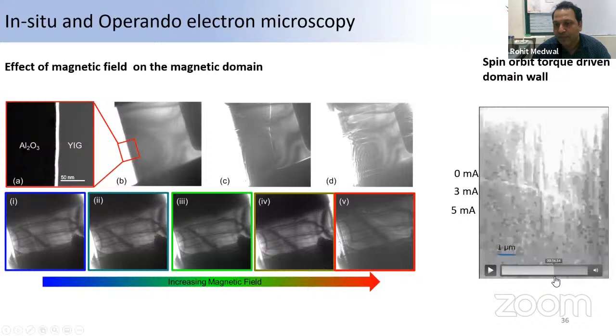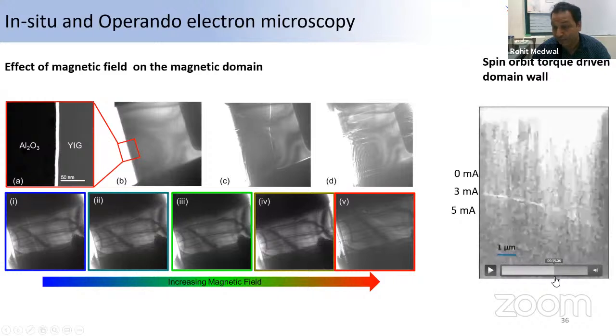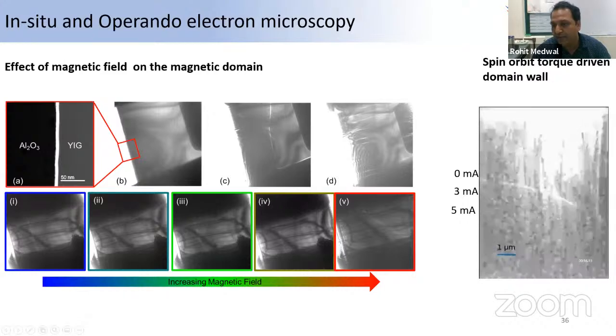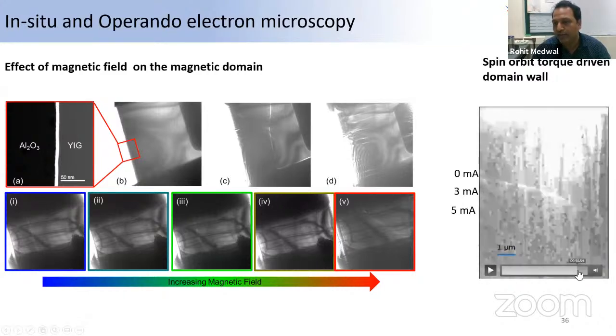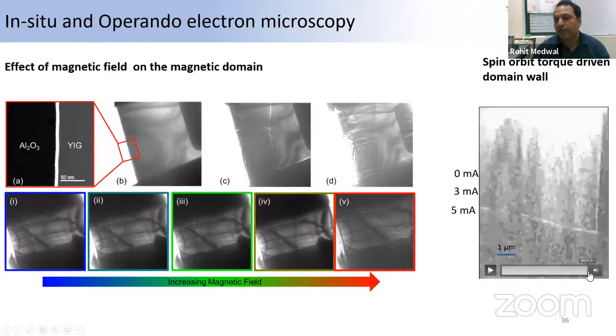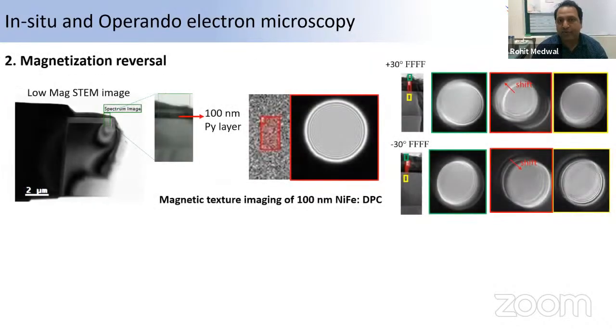You can see here. Maybe I'll stop here. You can see that at 3 milliampere, we can move the domain wall here. And at 5 milliampere, it can really go to the final state, the third state. So we are able to successfully move the domain wall using the pure spin current, and we were able to detect this live in situ in the microscope. With this, we are also able to see the switching of the magnetization from one state to the other using differential phase contrast imaging, where we have this bright-field disk without applying a magnetic field. But when we apply the field in a different direction, we can shift this bright-field disk from one direction to another direction.